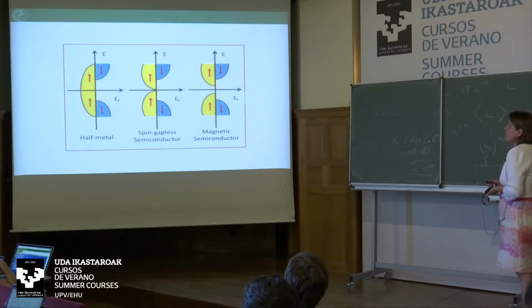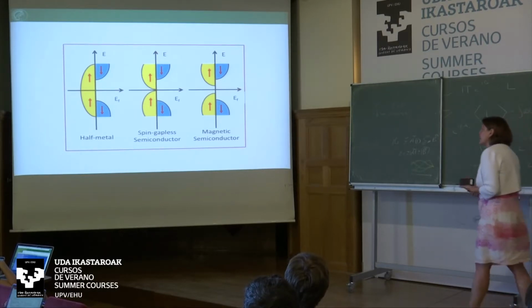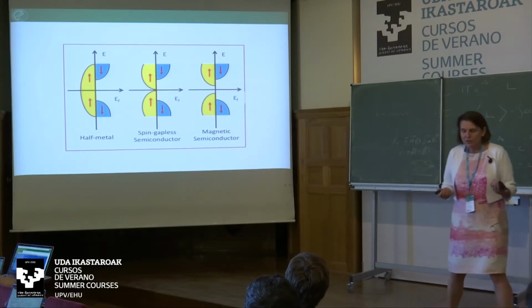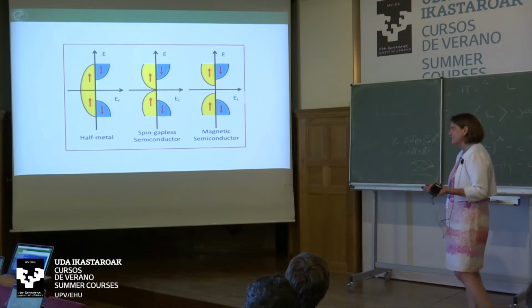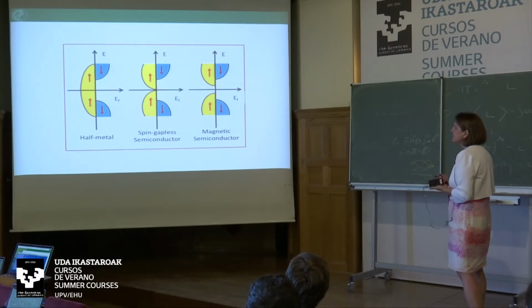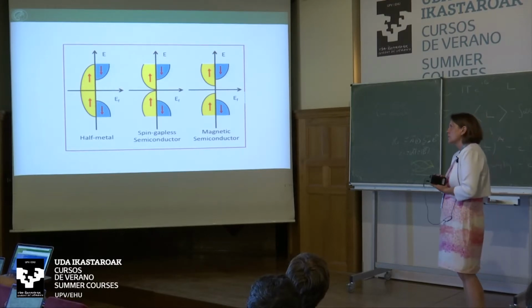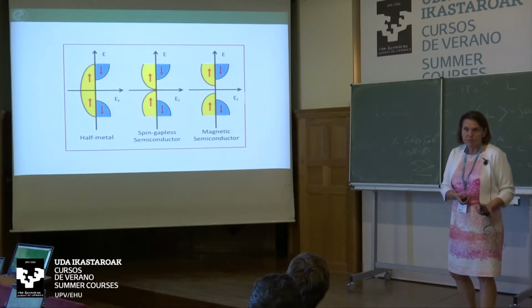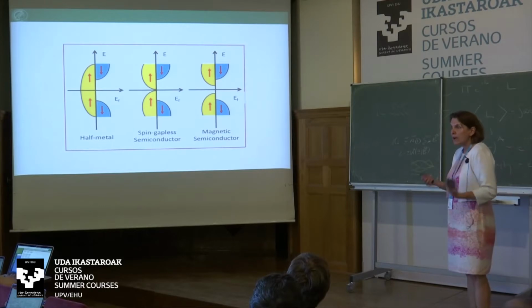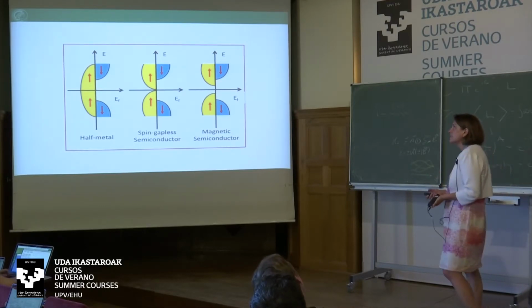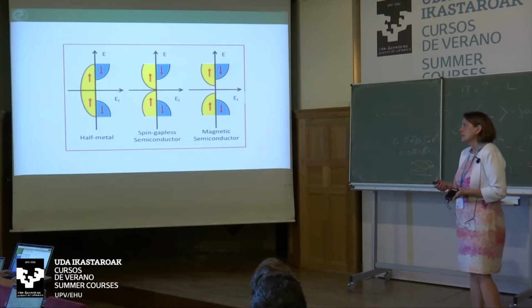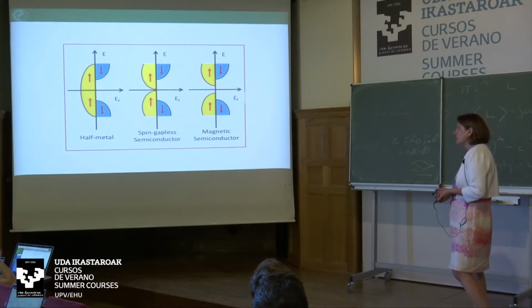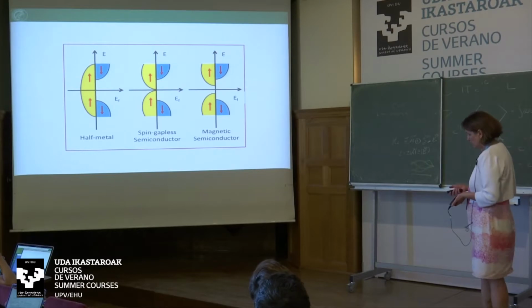We also have in these Heusler compounds quite some compounds which have gaps in both spin directions, which is surprising, because people looked for ferromagnetic semiconductors for many years. There were very famous people, but they always had to dope, which is what people do for the quantum anomalous Hall effect. Nowadays, they take a semiconductor and dope some magnetic ions in there. But then you do not have a real magnetic compound, you have a doped compound. And the TCs they reached in gallium arsenide doped with manganese went up to 180 Kelvin, and then it's already metallic, and you know the low TCs from the bismuth doped compound.